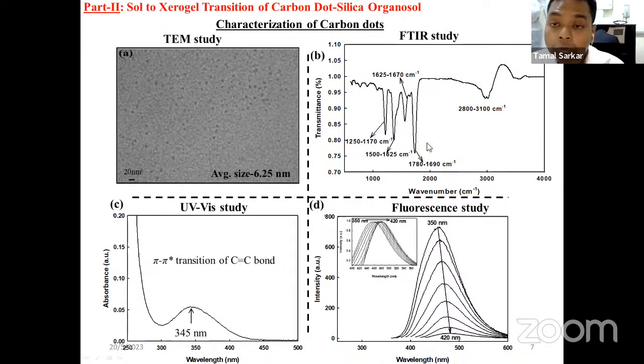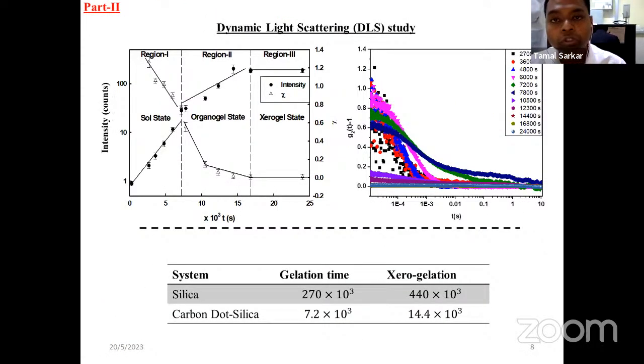The FTIR study confirms the formation of carbon dots due to this signature peak, which is a peak for COO of the carboxyl group. The UV visible and the fluorescence study also indicate the proper formation of carbon dots. Now, moving on, after incorporation of the carbon dots, what happens to this sol to gel and gel to xerogel phenomena? Again, I have taken the dynamic light scattering study, and I have plotted the intensity profile and the chi, the ergodicity parameter profile.